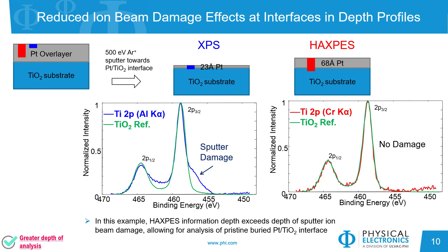As shown here, we would like to analyze the platinum–TiO2 interface, but the top platinum layer is too thick. Using a 500 eV argon beam, we can sputter toward the interface. With XPS, by the time we detect titanium, we see chemical reduction due to the ion beam. However, with HAXPES, we can detect the titanium with a thicker remaining top layer, and so the interface TiO2 chemistry is preserved. This is a major advantage of using HAXPES for depth profiling.